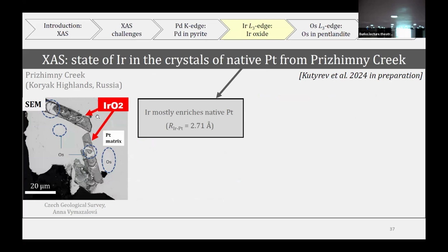We also performed the exact spectra fitting, but I'm not showing it because it will be quite repetitive, so I will be showing only the results. So iridium mostly enriches their native platinum, and this distance is extremely close, the iridium-platinum to platinum-platinum distance in the metallic, in the pure platinum phase. So as expected, I would say.